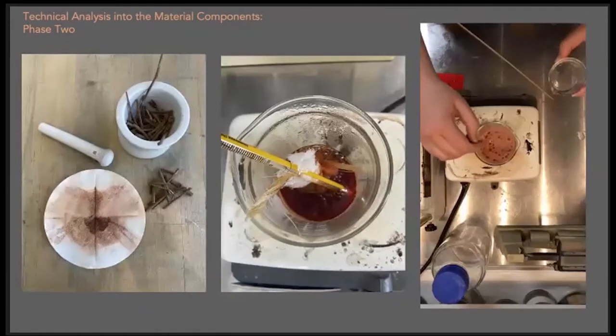The second dye was created from madder root, which is largely sourced from the Middle East and Eastern Mediterranean. The material itself is more complex than cochineal, and its preparation requires a more careful control of temperatures through the extraction process. The root was cut into small pieces and, like the cochineal, ground. In order to extract the dyestuff, the natural material was placed in boiling water, filtered, then an alkali and metallic salt are added.